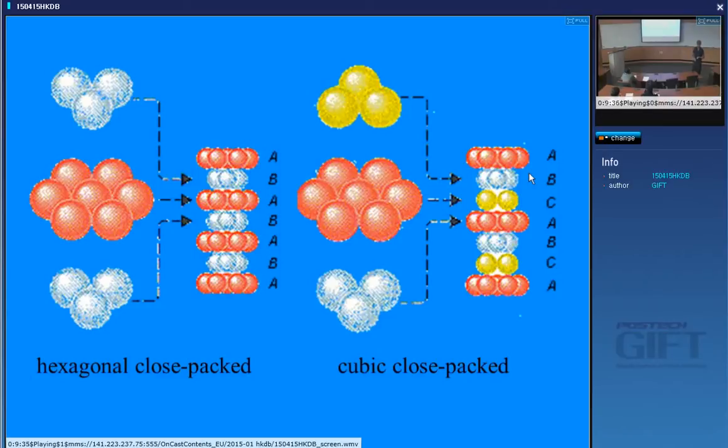Okay? When you look at the structure of hexagonal close-packed iron, it's basically taking the austenite. So we have ABC, ABC stacking of the 1-1-1 planes. Yeah? If we alter that stacking sequence into AB, then we get the hexagonal close-packed iron.